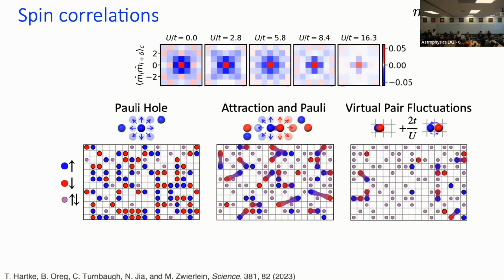And for very strong interaction, the correlation length decreases again, because now I have such a high energy cost to fluctuating to the neighboring site where I'm not profiting from the attraction, that it's very strongly suppressed. And therefore I get only a small next neighbor correlation here in the high U limit. Cool, so that actually is the picture.